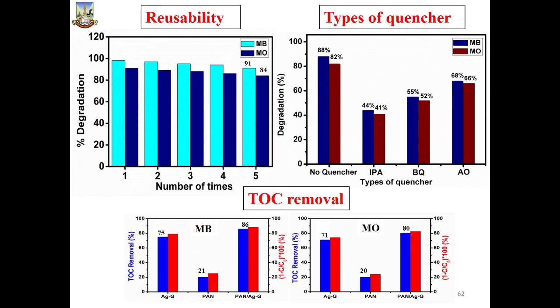We have done the TOC removal study in the case of methylene blue and methyl orange. For silver grafted material, TOC removal is 75% as compared to PAN, and PAN/Ag-G shows 86% TOC removal for methylene blue, but for methyl orange it is 80% TOC removal.